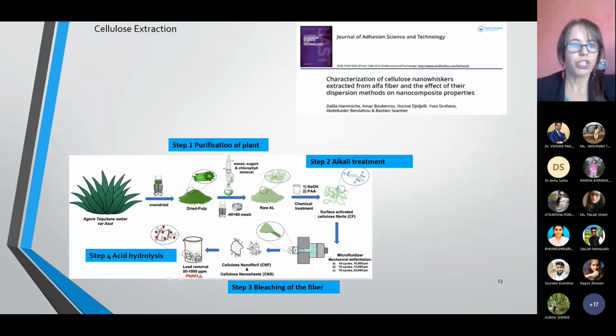The last step is acid hydrolysis, as I said, where we have to remove the amorphous region. Hydrolysis was carried out with sulfuric acid to remove the non-crystalline regions, leaving a collection of well-dispersed microfibers. Here we can add, according to this paper, a 5th step if we want, because at this 4th step we will obtain microfibers. If we want to obtain nanowhiskers or nanofibers, we have to complete the 4th step with a 5th step, which is sonication. Sonication can help us to obtain nanosized fibers. Okay.